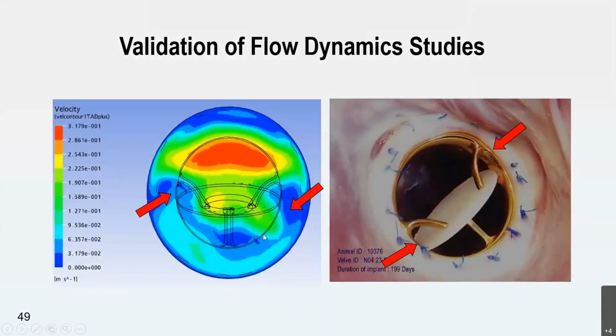Of course, this was validated by our studies in flow dynamics. You can see that in flow dynamics, we see 2 areas where, even though it is not negative flow, the velocity of flow is extremely low. And correspondingly, at those regions, you can see that the tissue is growing more into the frame than in the other regions. So, of course, this was presented at the World Biomaterials Congress, and it is a good reference for this particular work.